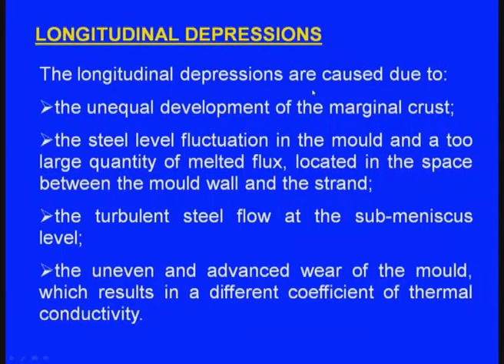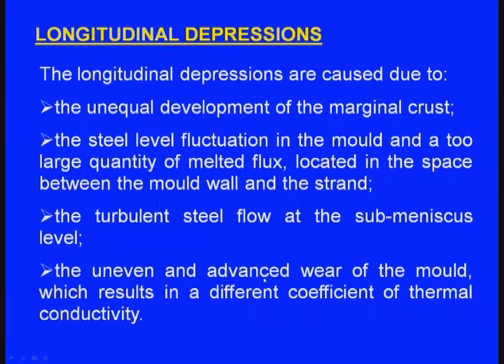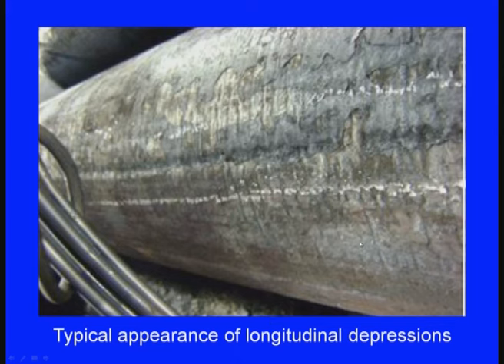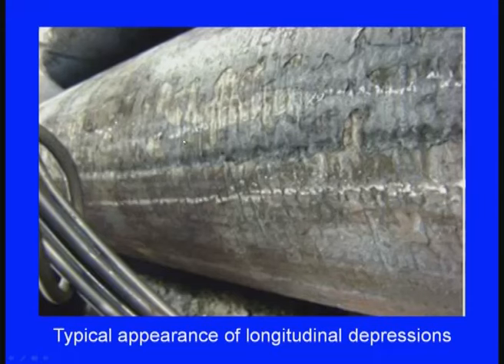Next, longitudinal depressions. These are caused by unequal development of the marginal crust, steel level fluctuation in the mold, a too large quantity of melted flux in the space between the mold wall and the strand, turbulent steel flow at the sub-meniscus level, and uneven and advanced wear of the mold resulting in a different coefficient of thermal conductivity. Longitudinal depressions are parallel to the axis of the bar — these depressions are oriented parallel to the axis.